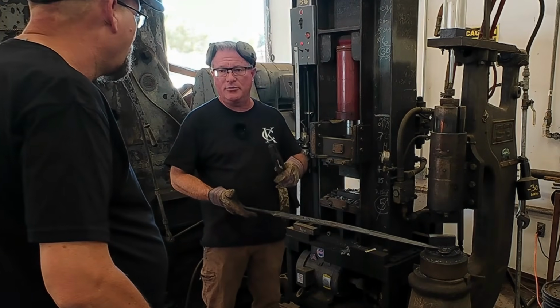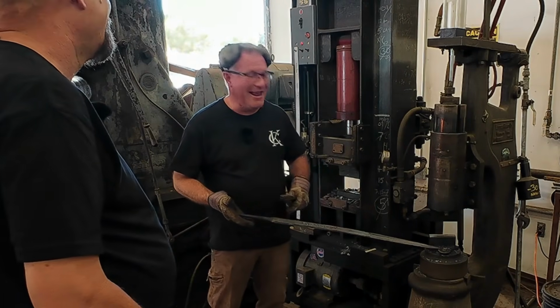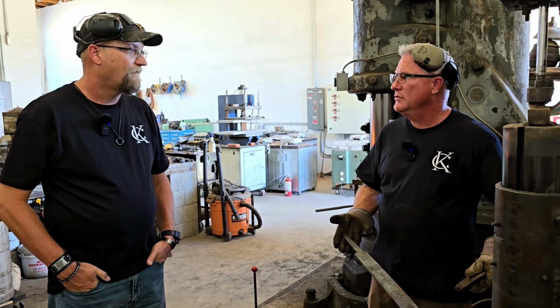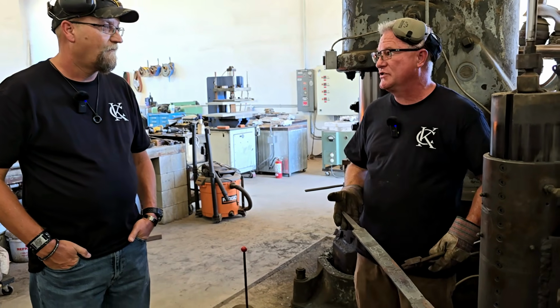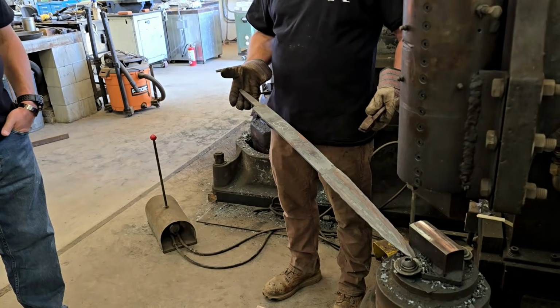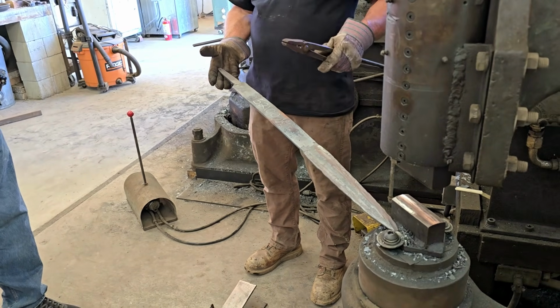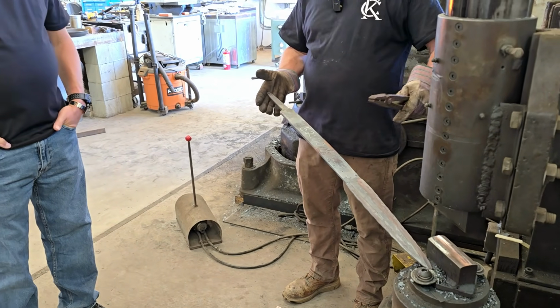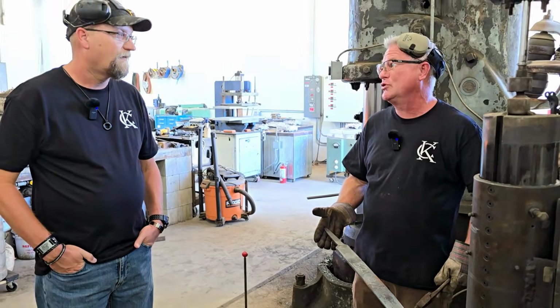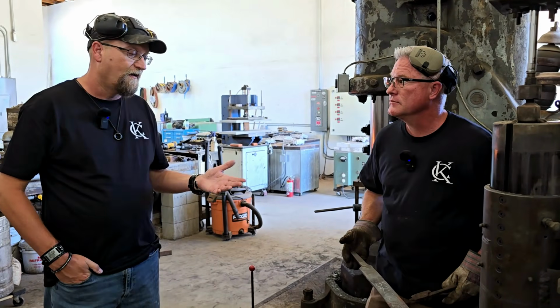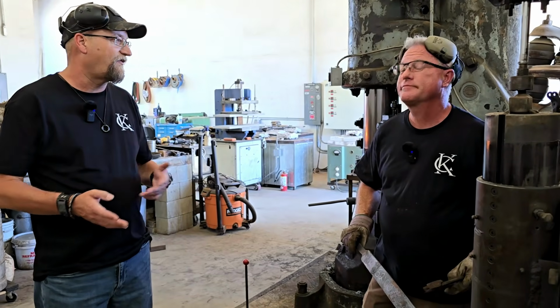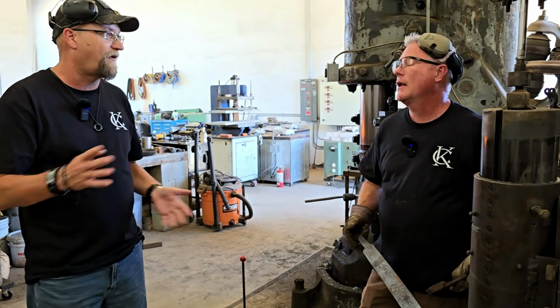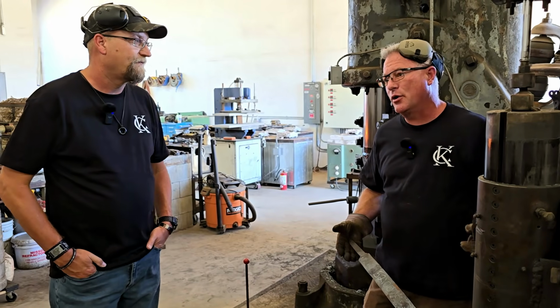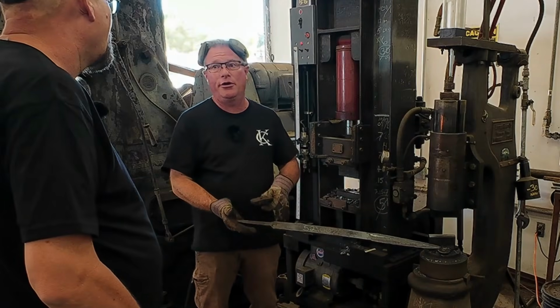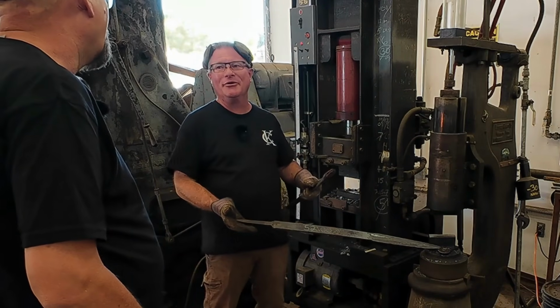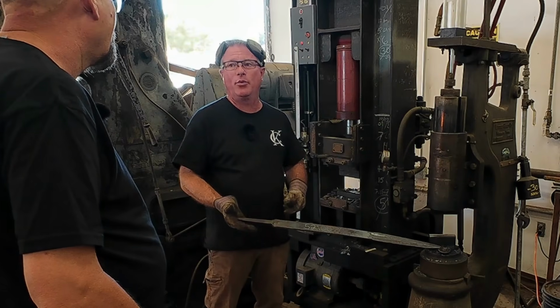So we go through this whole heat treating process to make it soft, and to even out the grain structure, because forging in a lot of ways can screw up your grain structure. It can wreck things. The heat treating after that is not the hardening part, but it's still a heat treat. You're fixing what you screwed up forging it. Right, and I also imagine no two hammer blows are going to be exactly the same or aligned, so you're introducing uneven stresses all over the place. Right. And that's where that heat treating stage prior to hardening comes in. It's kind of weird, but that stage is very important.